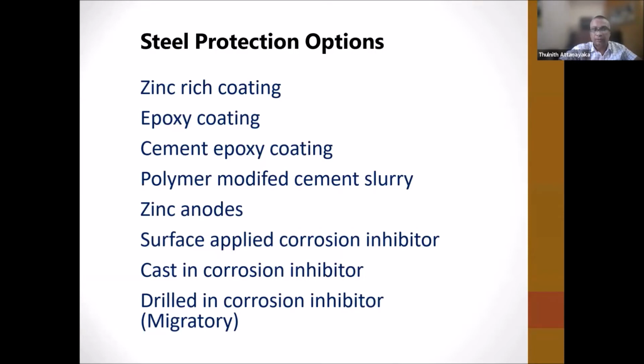As we all know, this epoxy is very shiny, very durable and very seamless. But with this epoxy, you have a concern. We have to ensure proper bonding between the coated reinforcement bar and the repair mortar. Other options are cementitious epoxy coatings, polymer modified cement slurries, zinc anodes, surface applied corrosion inhibitors, and cathodic protection using a more active element like magnesium that we can attach to the steel, and drilled-in corrosion inhibitors.